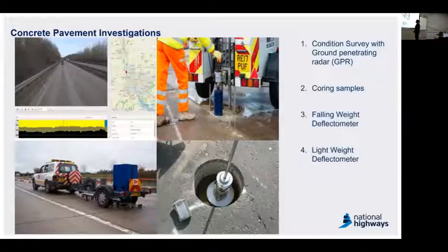The one on the right-hand top corner is the usual old school technique. We take a core sample just to understand what the material is, the thickness of it, and what sort of defects we are looking at. That gives you this kind of information. The one on the bottom left is called the falling weight deflectometer. We use it widely on both asphalt and concrete. For concrete, mainly we use it for understanding the load transfer efficiency between the slabs. Once you have a joint in between, it's important to understand how exactly we are transferring the load from one slab to the other. Dowel bar issues or even some loss of support could lead to poor load transfer, which means each of the slabs gets isolated and starts to deteriorate quite a bit faster.